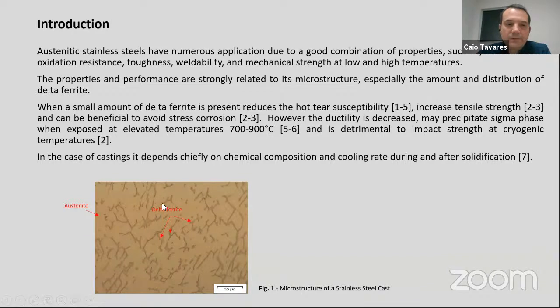Usually, this small amount of delta ferrite is very helpful to reduce hot tear susceptibility. When you weld austenitic stainless steel, if it is 100% austenitic, you may have hot tears, or also during the casting process. This delta ferrite also increases the tensile strength and can be beneficial to avoid stress corrosion. However, the ductility is a little decreased and sigma phase may precipitate when exposed to elevated temperatures. So we need to be very careful about the amount of delta ferrite in the stainless steel, according to the application.